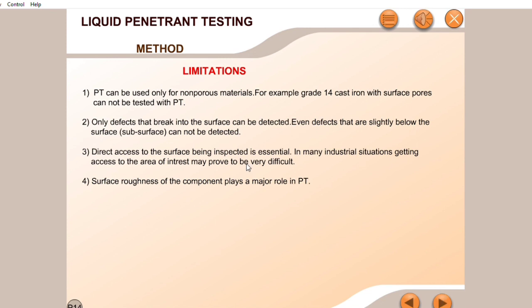Okay, limitation side, there are some limitations, like as I told you that liquid penetrant testing can be performed on non-porous material. There are some materials which are porous in nature, like cast iron, so you cannot perform testing on cast iron, and you cannot get the proper result in cast iron. Okay, the second point, only defects that break to the surface can be detected. Any defects which do not break to the surface, maybe subsurface or inside of the component, you cannot get the result. So the limitation is only surface-breaking indications you can find by liquid penetrant.